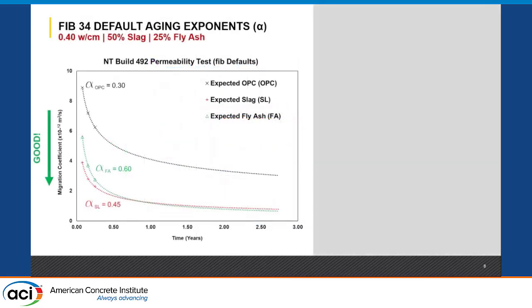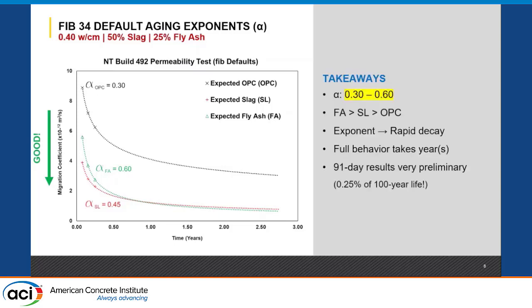This is what a default plot looks like for 3 materials: straight cement, fly ash, and slag. And again, good is down. So you can see that green, the fly ash, is the one that goes the lowest. We see that these alpha values are between 0.3 and 0.6. The higher the alpha value, the more it's going to go down. It's an exponent. It acts up really fast, but again, it takes a couple of years for it to get to a more final section.